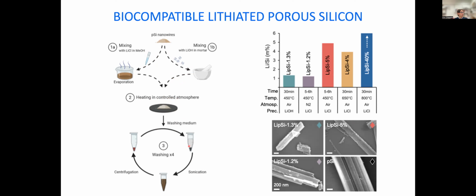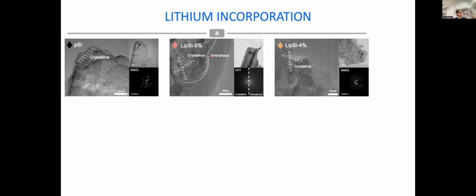And then the material that we obtain, we go ahead and we dissolve it fully to evaluate how much lithium to silicon we can obtain. And we do that with nanowires, okay? Because they're easy to obtain, they're easy to porosify by metal-assisted chemical etching. And in that way, by controlling the lithiation parameters, we can obtain anything from 1% lithium all the way to over 40% lithium within our porous silicon. So we have a much broader range than what can be achieved with conventional bioglasses.